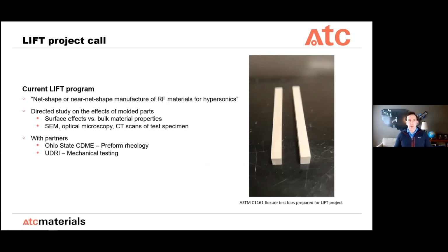So we can use those surface effects to manipulate the material in an advantageous way to create a grain alignment, structure alignment, different densities, things like this. But if we're not trying to do that, are there any differences between the surface microstructure and the bulk material microstructure of the material? The image on screen there is one as-molded and one molded and machined part. But we're going to make, in this case, ASTM flexure bars.